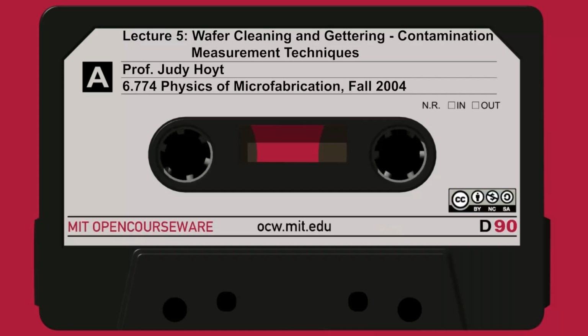Fourth type, QOT, oxide trap charge. This is represented right here. It's in the bulk of the oxide. Notice it's drawn up here. It's not at the interface. It may be created by other processes that the oxide was subjected to after it was grown. The oxide might have been subjected to plasma etching. Plasma could put traps in because the plasma has energetic ions going into this thing.